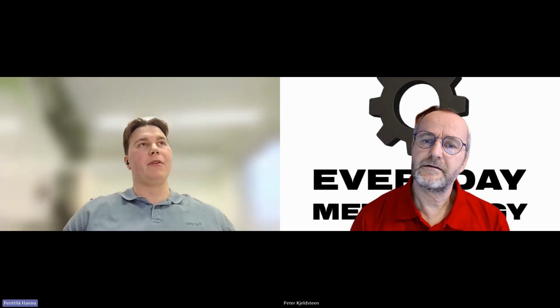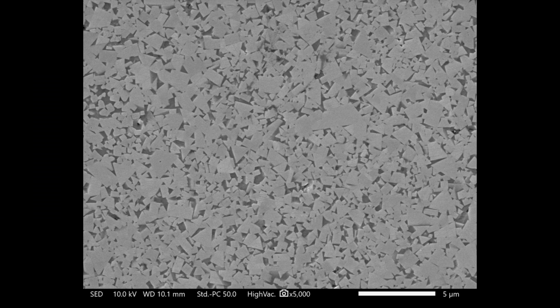That's high. So, is it an argon or active atmosphere? It depends. Argon, yes, it's a common one. Also vacuum. Vacuum sintering is common for these, or some kind of argon plus hydrogen, a mildly reducing atmosphere might be used. So regarding the question, the carbon balance is something that is crucial for these hard metal components to prevent that eta phase from forming. So it's a brittle phase, and it's not wanted for these applications of hard metal components.